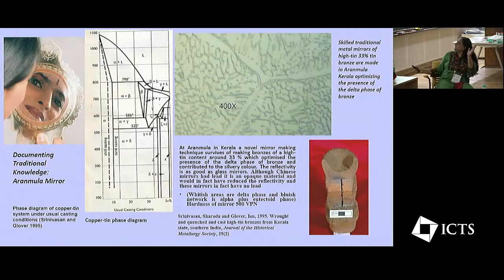So here typically you're seeing a traditional crucible cum mold, which is used to cast this delta blank. This is a two-piece mold with a very narrow space, so that a very thin blank is cast, the heterogeneities are limited, and you get a very homogeneous casting. I call it a crucible cum mold because on top of this crucible cup is where the metal to be cast is placed, and then the whole thing is closed. And then we see the casting.